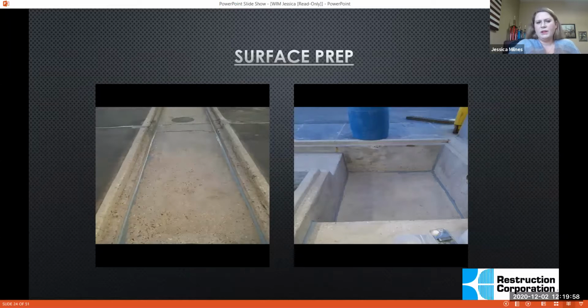So what we have to do in an environment like this is we go in and we remove whatever coating is left, and then we actually hand ground this, whereas on the other projects we use things like jackhammers and so on to get the surface prep that we are looking for. So this actually is hand ground, so it's a really low profile. And then we take the same material that we're going to coat it with and we thicken that up with fumed silica and we fill in the cracks. If you see on this picture on the left, you see the big cracks. That is where this acid is getting into their structure and then into the ground. So what we're trying to prevent is not necessarily just the delamination of the structure. We're trying to stop that acid from getting into the ground.